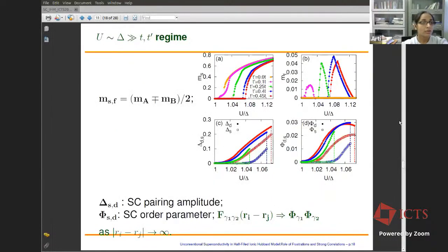And now we go to the limit of interest where we will see superconductivity. So let's look at the limit where the electron-electron interaction is comparable to the staggered potential, and both these energy scales are much larger than the hoppings involved in the model. In this limit, if we solve the effective low energy Hamiltonian that we obtain from a generalized Schrieffer-Wolff transformation using Gutzwiller projected renormalized mean field theory, we see that as you increase the strength of the next neighbor hopping, the strength of electron-electron interaction that you need to turn on the magnetic order increases. That is very clearly visible here: as you increase the next neighbor hopping from 0.1 to 0.45, you see that the transition point shifts towards the right.